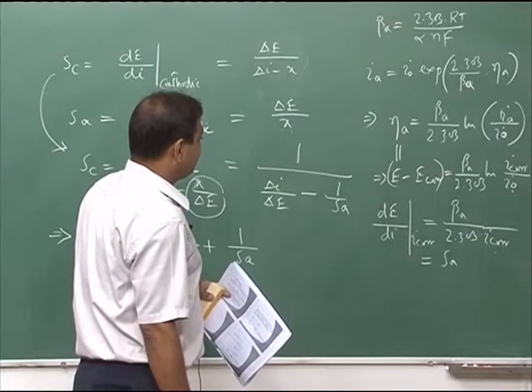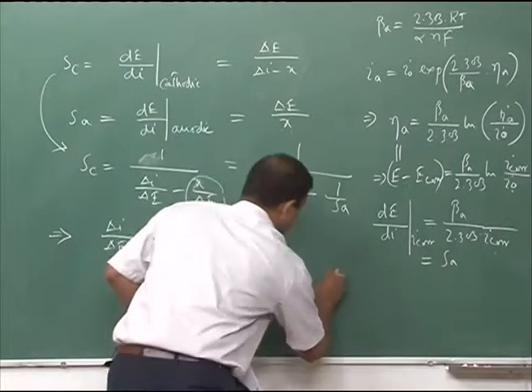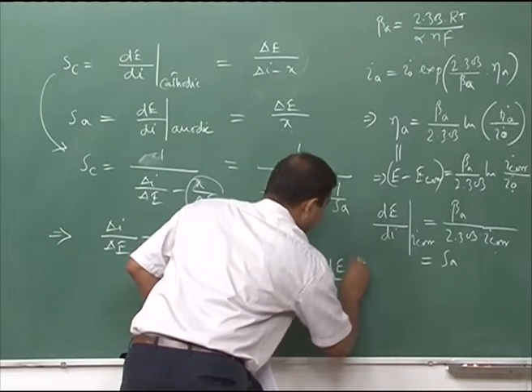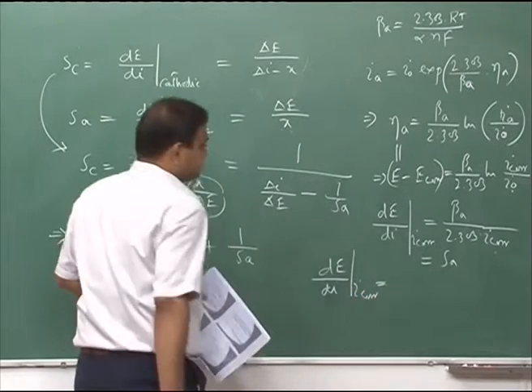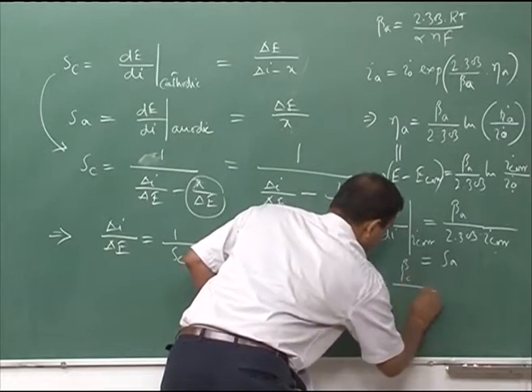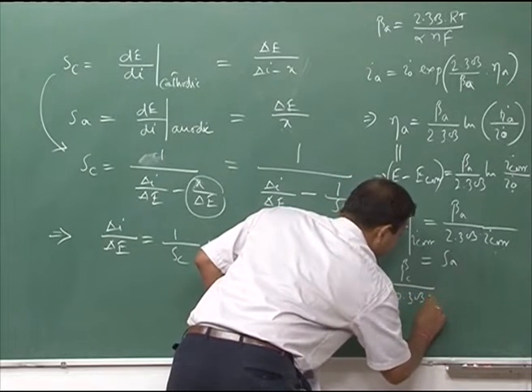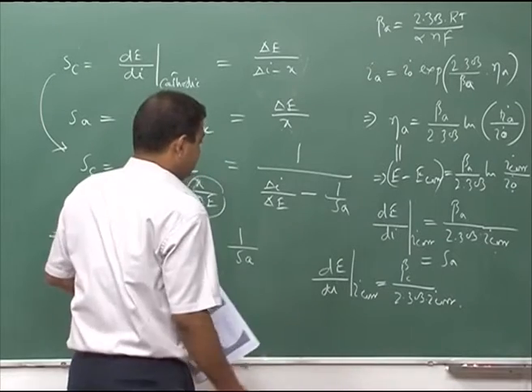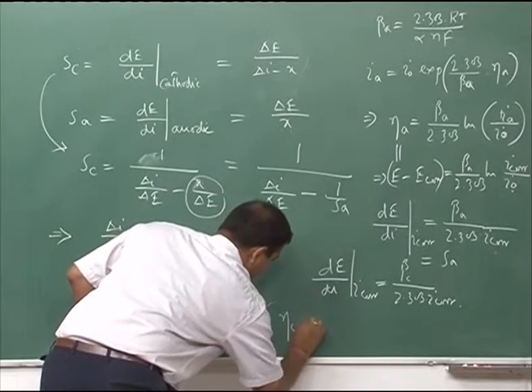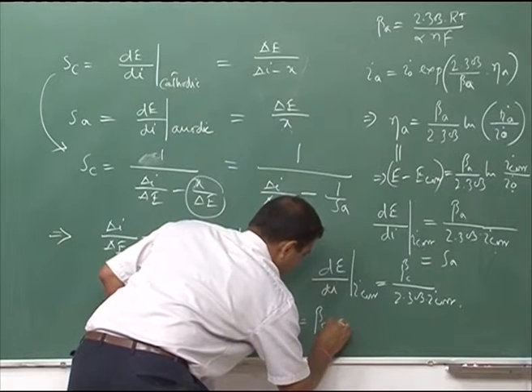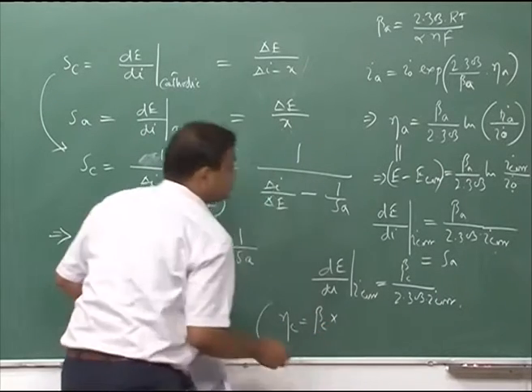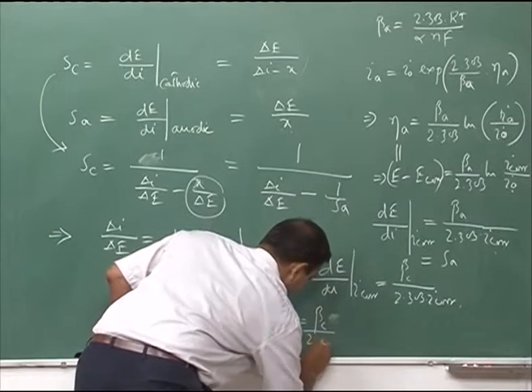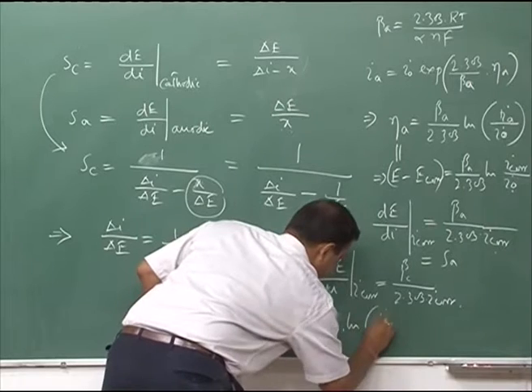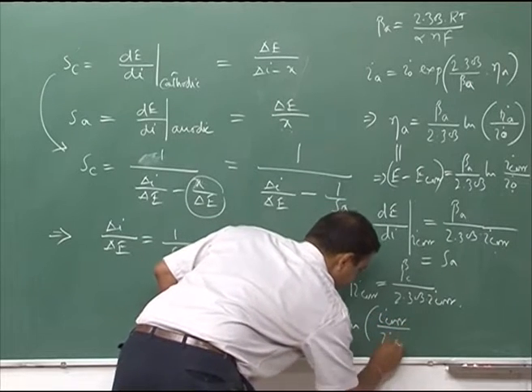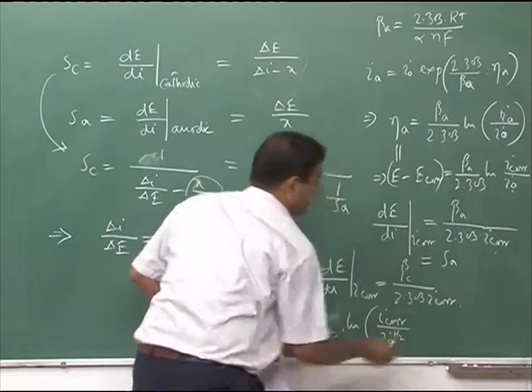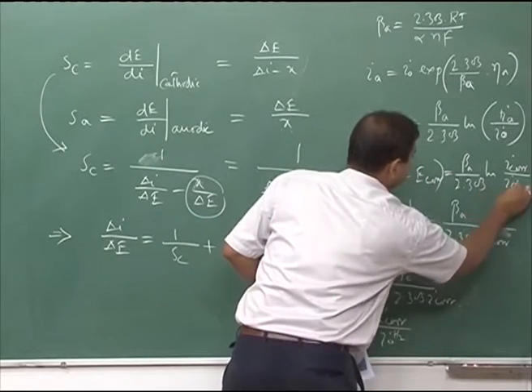Similarly, we can find out for beta C, that time del E by del I for cathodic reaction, it would be beta C divided by 2.303 I corr, and that time we start with beta C into divided by 2.303 ln I corr divided by I 0 for hydrogen, and this is for metal.